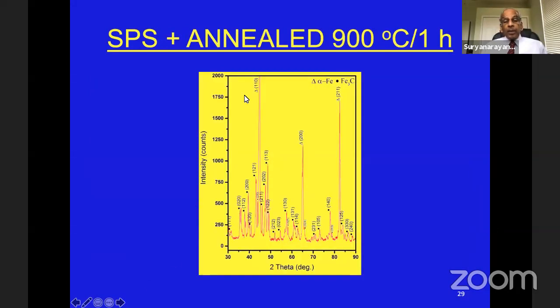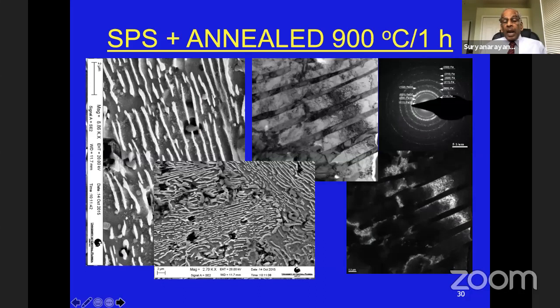Now, if you look at the microstructure after annealing, that means it is subjected to spark plasma sintering and then annealed at 900 degrees for 1 hour, you still have the same phases, although the proportions of the phases are slightly different, but essentially the same two phases continue even after annealing. Now you see the lamellar structure, the eutectoid lamellar structure, very clearly after annealing, because the very, very fine grain sizes would preclude the formation of this lamellar type of microstructure. And that's the reason why only after annealing, you can see it very clearly.